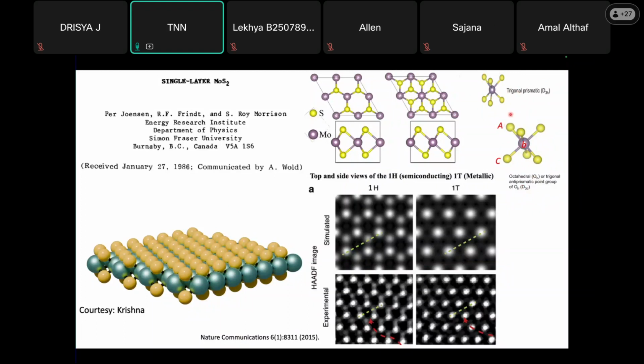Now, how do I identify? There are various ways. Both of them have very specific phonon modes, which are very sensitive to their phase. So you can look into the Raman spectrum, Raman analysis, to see which phase is being formed. Or with the electron microscope you can see.